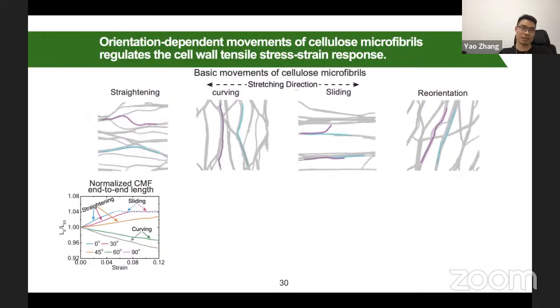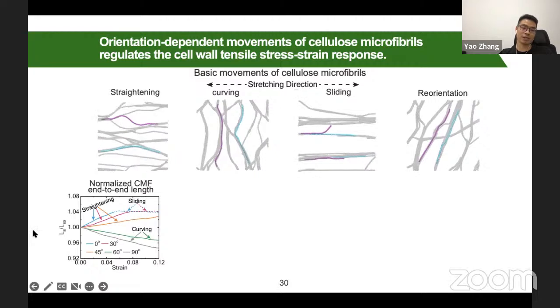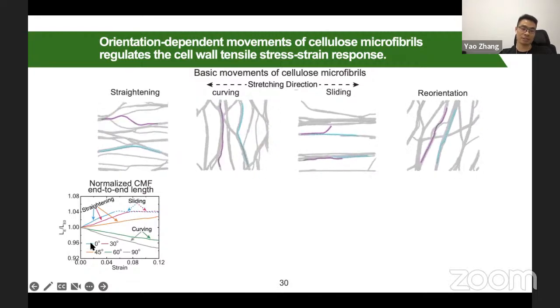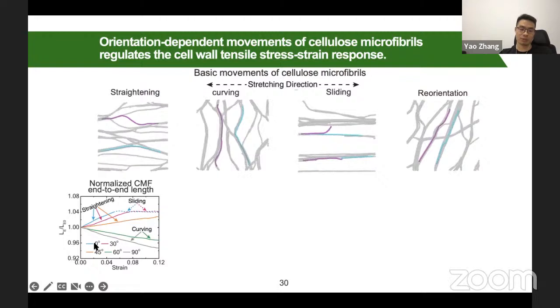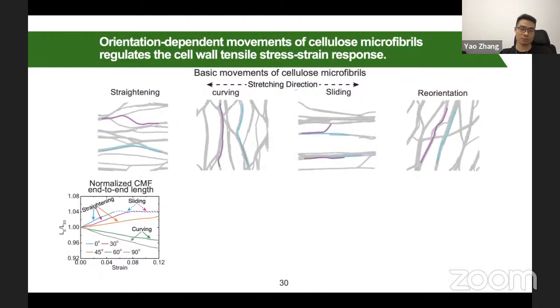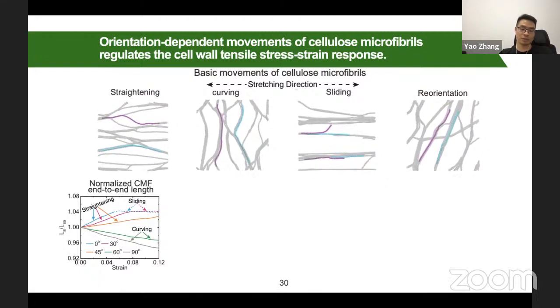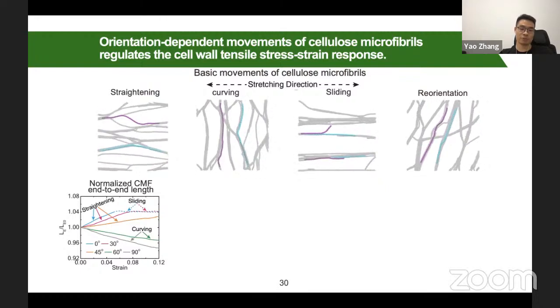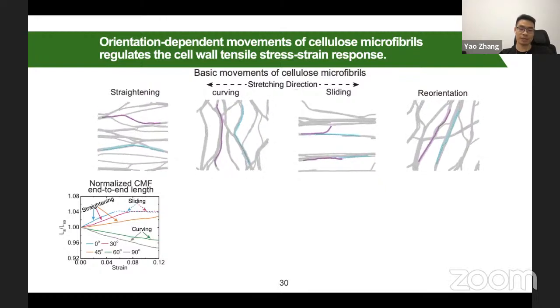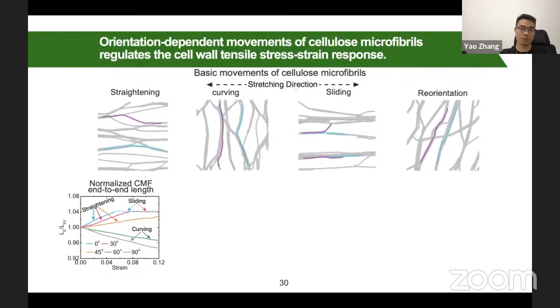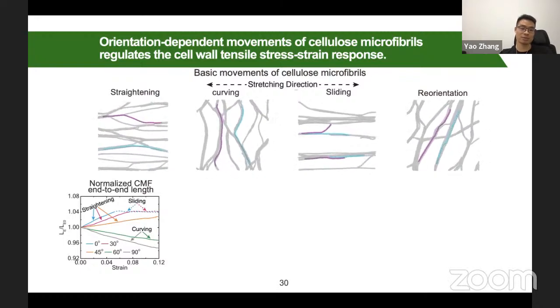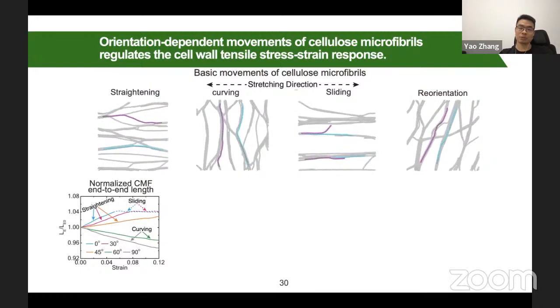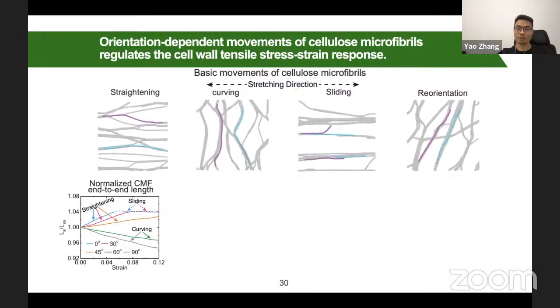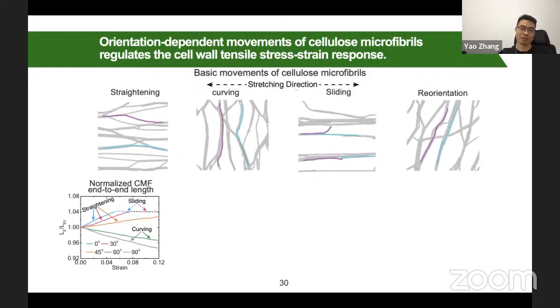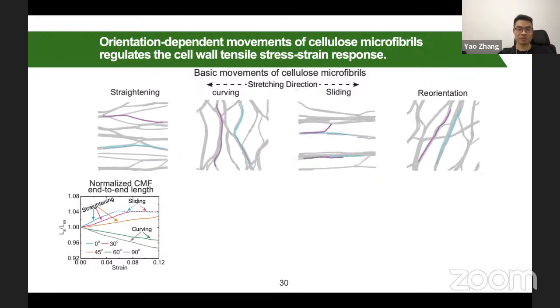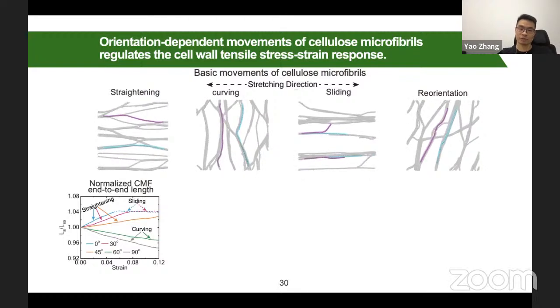The cellulose has five single layers. Each single layer has a uniform orientation, which is 0 degree, 30 degree, 45 degree, 60 degree, and 90 degree. So if you look at this 0 degree, it means that you stretch your layer which has cellulose fibers, and the cellulose fiber orientation is the same as the strain direction.